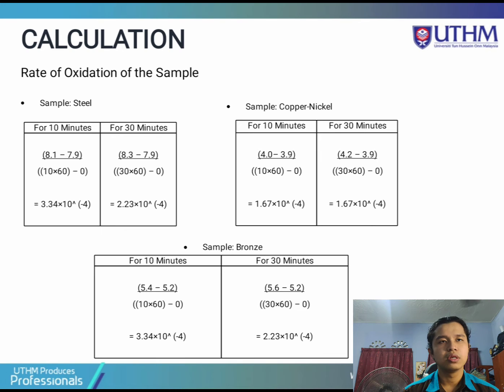For the sample copper nickel, for the 10 minutes duration, 4.0 minus 3.9 over 10 times 60 minus 0. The answer is 1.67 exponent negative 4 gram per second. For the 30 minutes duration, 4.2 minus 3.9 over 30 times 60 minus 0 equals 1.67 exponent negative 4, which is the same rate of oxidation for the durations of 10 minutes and 30 minutes.